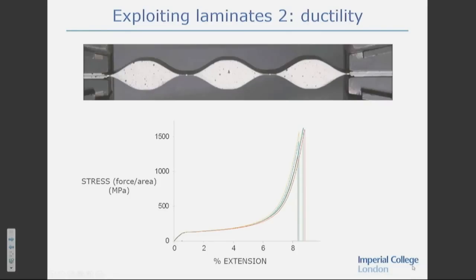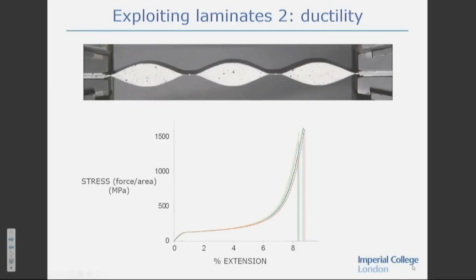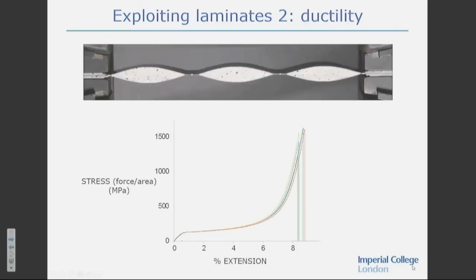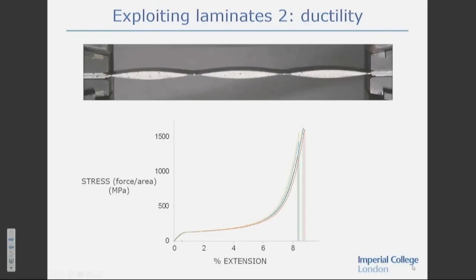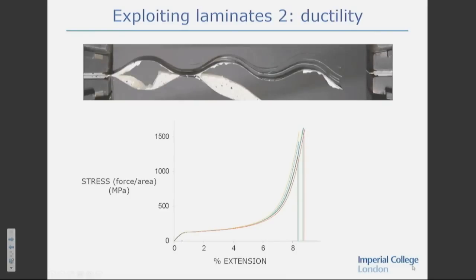At the top, here's an experiment performed on one of these wavy sandwich panels with 3 of these cells. And you can see what happens. We get exactly the behavior we predicted. Each one of these is crushing simultaneously and finally goes bang, okay? And the good thing is here, we're getting strains up to 8.5% here. These are very large compared to the strain to failure of the carbon composite on its own, which typically fails in the range of about 1 to 2%. Okay? So you can see we can introduce ductility by exploiting that laminated architecture.